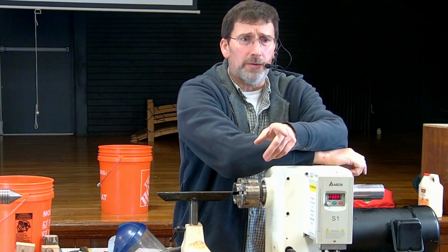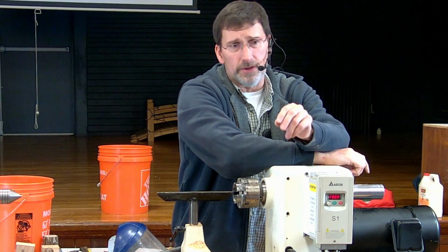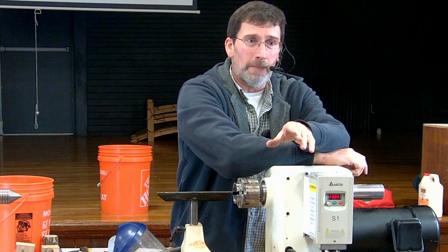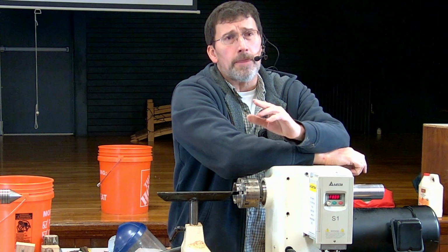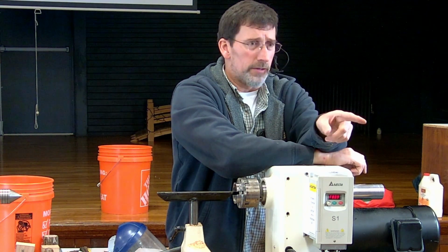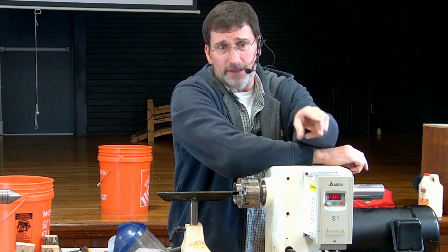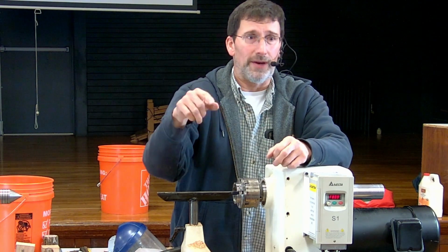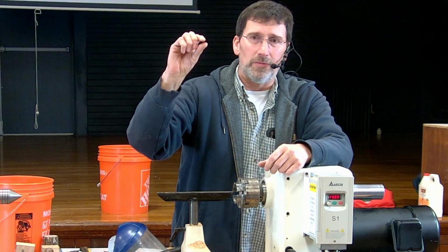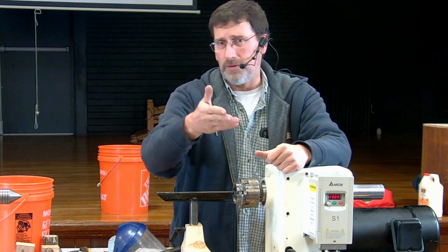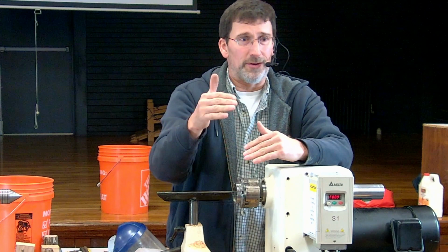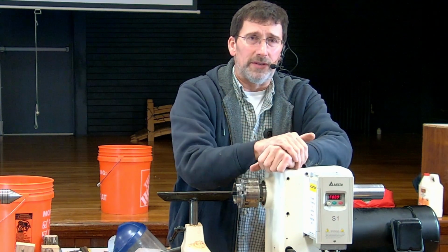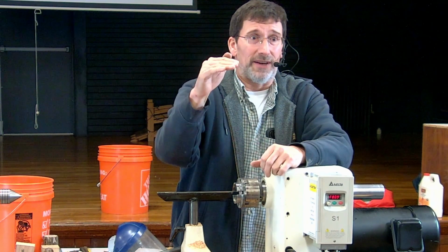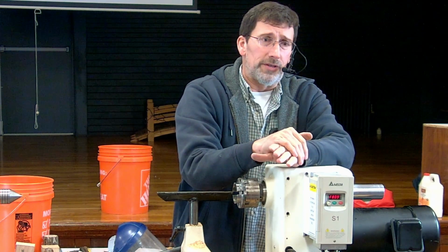I worry about the blue. And with these tools, you can easily turn them blue when you go aggressive. If you do that, you look at the heat tint chart that went around. That'll tell you, roughly, that you were at 600 or 700 degrees, which means you've really dropped the hardness down, and it won't hold an edge as well.